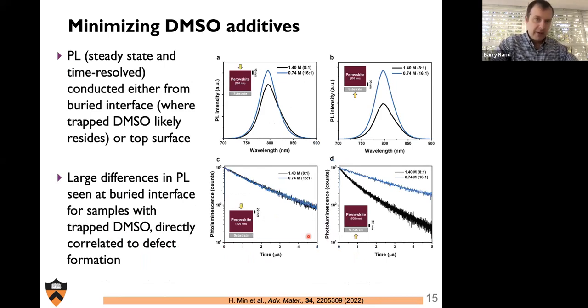Showing that this leads to differences in devices, we first turn to optical techniques and photoluminescence. So turning your attention to the top panels here, what we did was monitor the steady state photoluminescence output of this perovskite film, either when excited from the top or excited from the bottom. And the reason that we did this is we were certain that the DMSO additives were almost entirely isolated to that bottom trapped interface between the substrate and the perovskite.